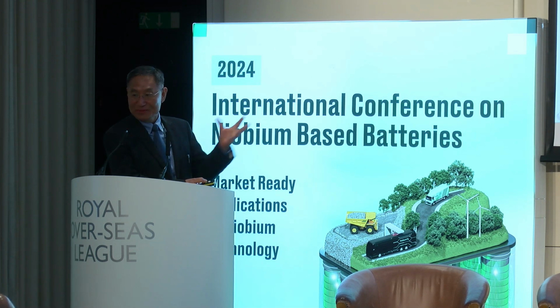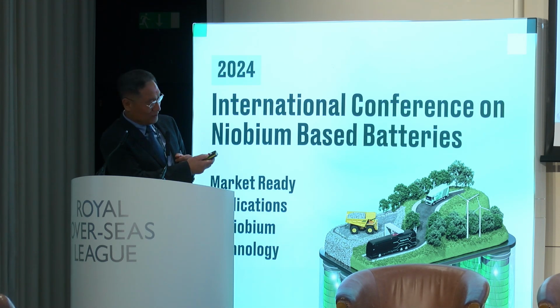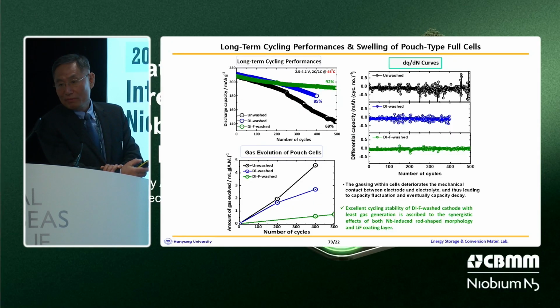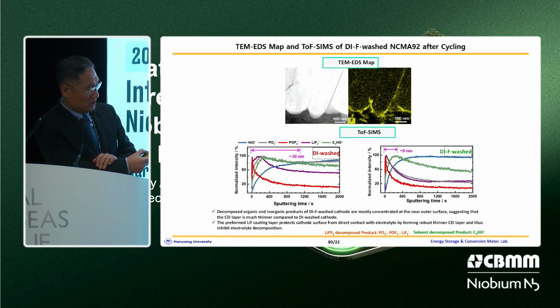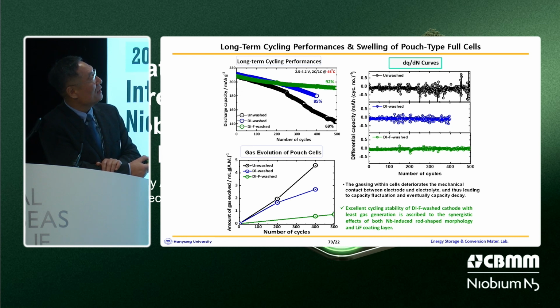Okay, it's good. Let's keep going on. This is the long-term cycle performance and the swelling of the pouch-type full cells. As you can see here, the unwashed cathode shows rapid capacity fading during cycling, and also the pouch cell containing the unwashed cathode increases rapidly in cell volume, and the DI-washed cathode exhibited improved cycling stability and slightly reduced gas generation. As expected, the cell containing the DIF-washed cathode demonstrates outstanding capacity retention of 92% with the least gas generation.